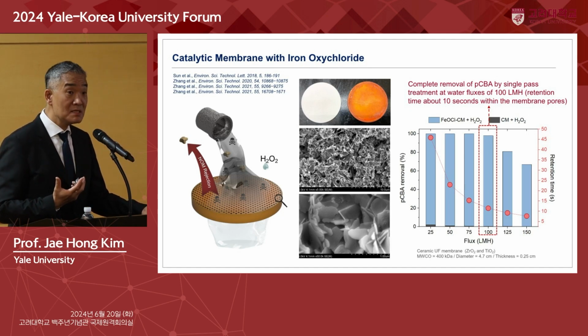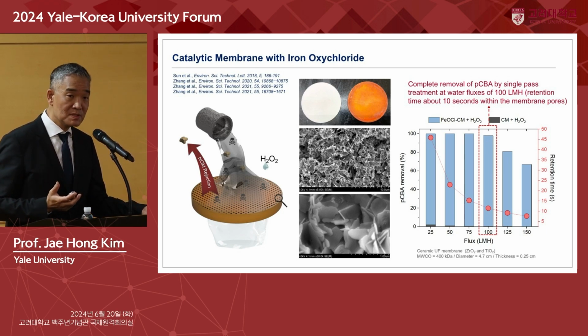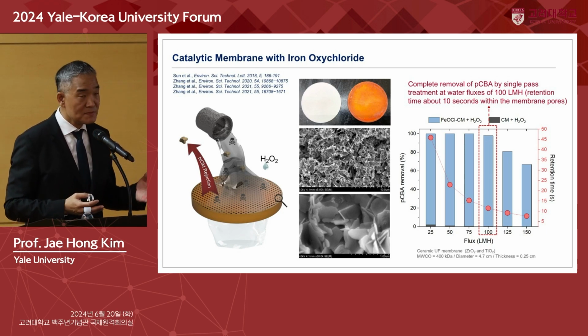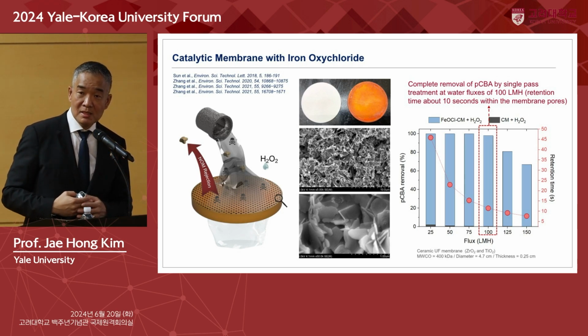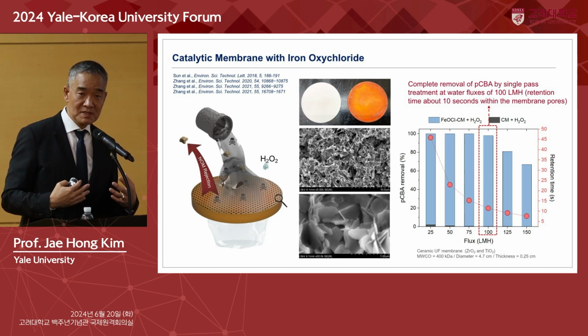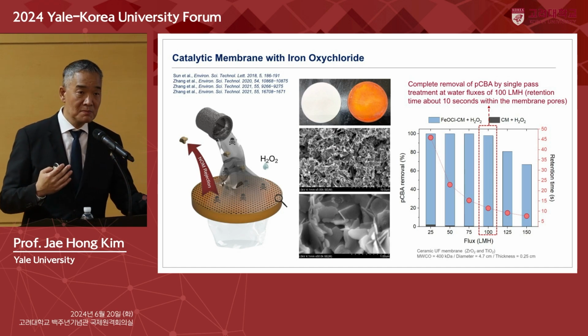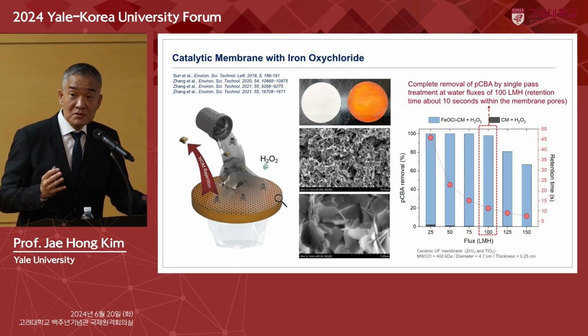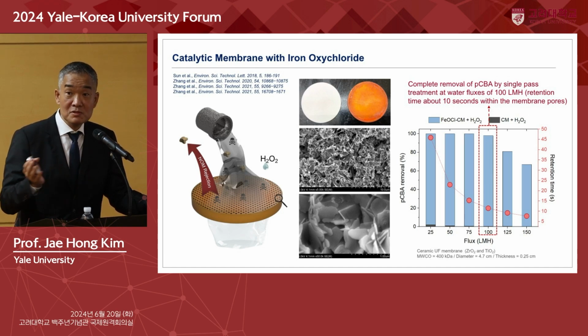The kinetics is super fast. We are talking about 100% removal of this pollutant within tens of seconds within the membrane. The kinetics was much, much faster than we typically observe in bulk phase. And this is called nano-confinement effect. I could talk about this for 1 hour, but I'm going to just skip now.